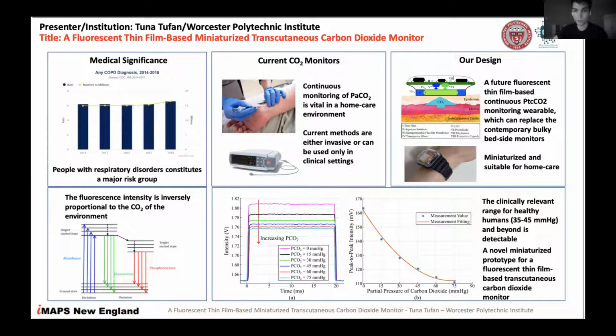And the prototype is envisioned as a wearable monitor, which will measure the carbon dioxide diffusing from the skin. It's also called the transcutaneous carbon dioxide. And we are using a carbon dioxide sensitive fluorescent thin film to assess the carbon dioxide level. In our benchtop experiment, the results showed that the fluorescence intensity of the thin film is inversely proportional to the carbon dioxide concentration. And the prototype can measure carbon dioxide levels within the clinically relevant range for healthy humans, which is from 35 to 45 millimeters of mercury.